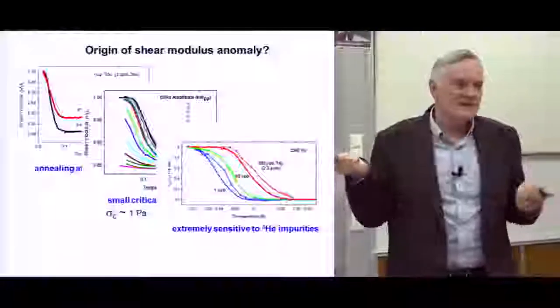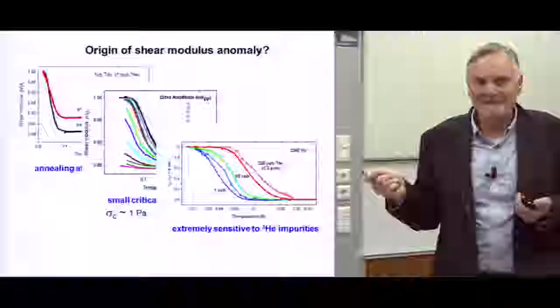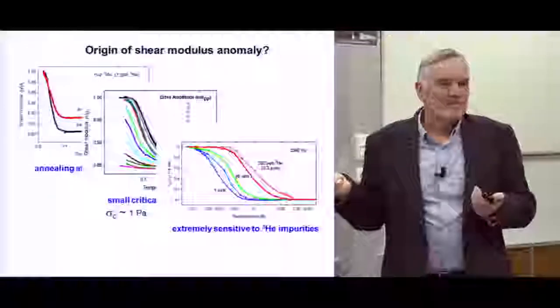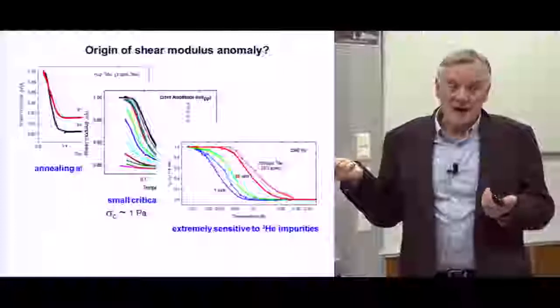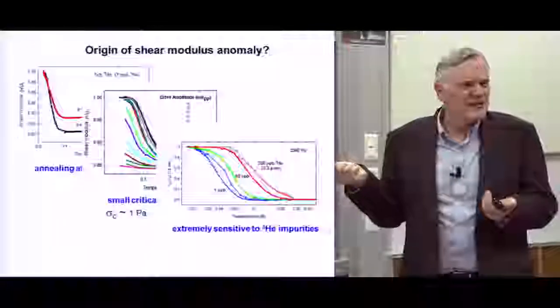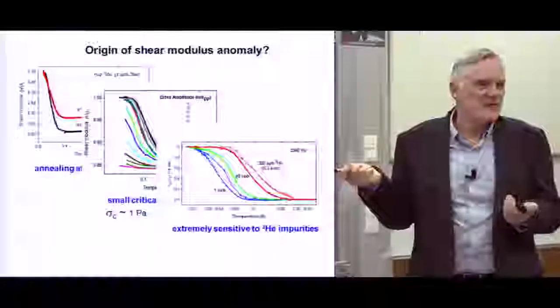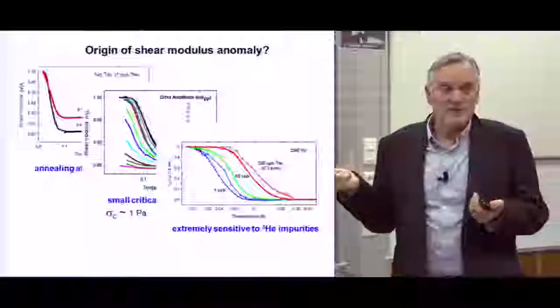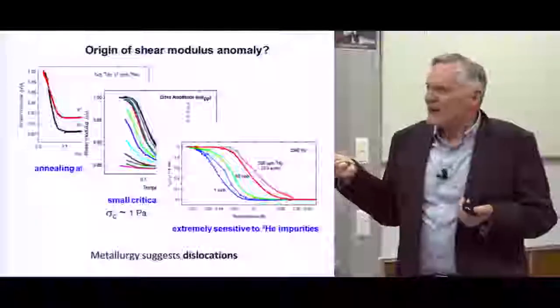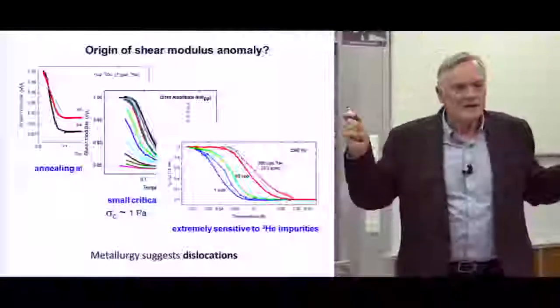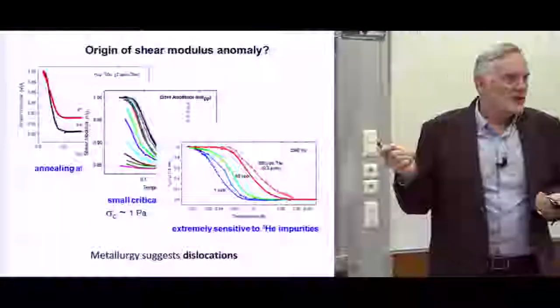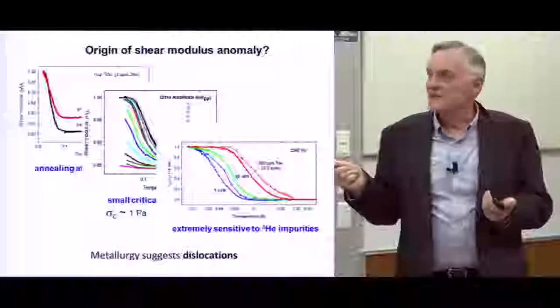In fact, in Sebastian's lab, they get rid of all of the helium-3, I believe. So it's a high sensitivity. And considering these are not chemically different, they're just the same atom, just a different isotope, and there are no other impurities. Okay, so metallurgists seeing this collection are going to immediately say it's a shear modulus. This has something to do with dislocations, because that's what affects elastic properties.